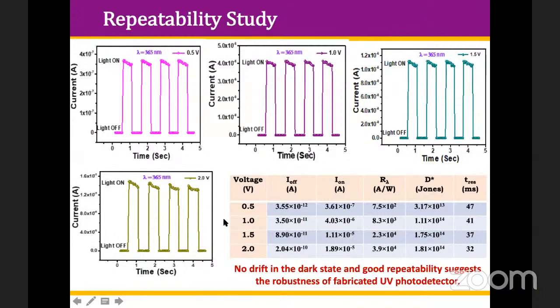So in this case, we have shown 5 cycles, but we can continue up to 20 cycles or 100 cycles. There is no change, no drift in the base current is obtained. And all these are the parameters obtained at different bias voltages, and you can see here the best performance which we obtained is at 2 volt in the system.